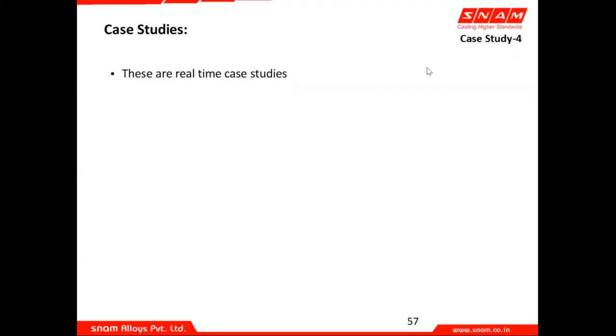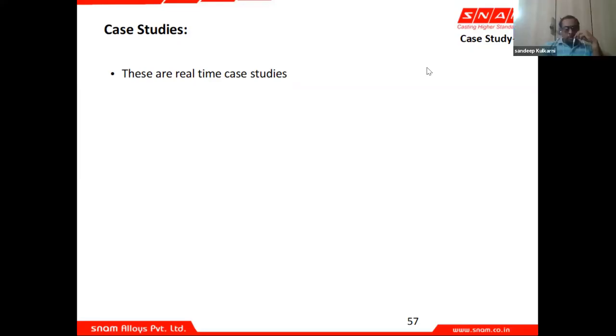Yes, sir. What is also a general recommendation? I think, sir, you are rightly saying that at least 5 to 10% pig iron is recommended. But in most of the areas, it is very difficult to get low sulfur pig iron, especially in the Kolhapur area, or the consistency of sulfur in pig iron is very difficult to manage. So in that case, whether preconditioning or anything will help in maintaining the consistency or the nucleation level in the metal.